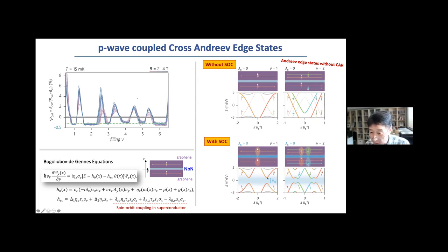And the important part is it opens up the gap, and this is basically a topological gap in the sense that it ensures there is a 0 mode inside, which actually mediates this Cross-Andreev process. Because of that, every time I add up this quantum edge state, I'm adding another copy of this type of topological gap with the 0 mode in there. In the simple view, regardless of the details of the size of this gap opening, as soon as the gap opens up and it's resolvable, I expect to see very similar CAR process happening, and that is what we are seeing experimentally, very robust CAR probability across the system.